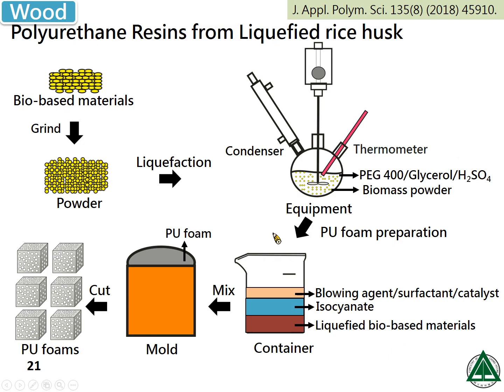We use polyethylene glycol and glycerol as co-solvent to liquefy the wood-based materials, for example, rice husk. So why do we use rice husk? The rice husk contains some silica. Moreover, we want to prepare polyurethane foam. So we add some blowing agent, surfactant, catalyst, and isocyanate and mix it, and we can get polyurethane foam and cut it. We can get the product.